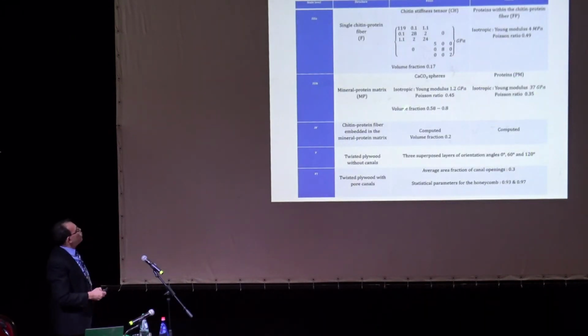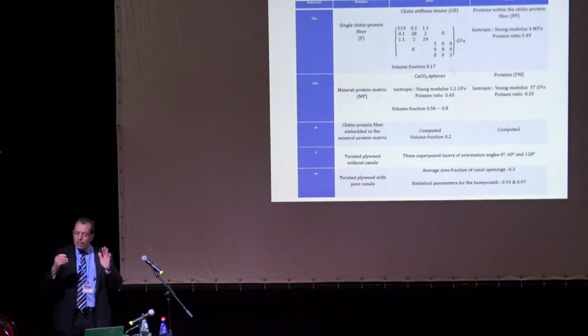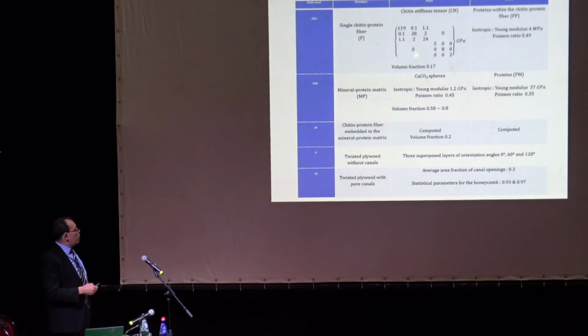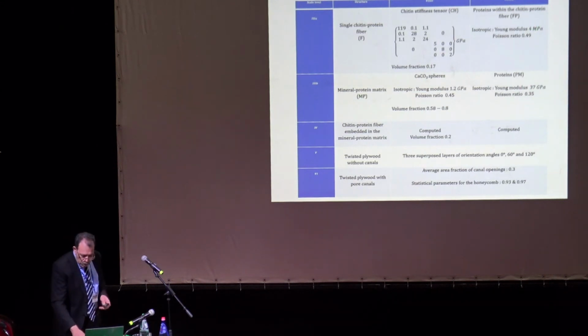Now, just to give you an idea of the properties, you have again a huge contrast here in the properties at different levels, okay? This is the elastic stiffness that they obtained from molecular dynamics, okay? And these are the properties of the matrix to get the fibers. Now at level 3, we have a matrix that has these properties filled by calcium carbonates with these properties, and so on. So we have all the properties here, but the most important thing to retain is we have a local anisotropy at the chitin level, okay, and also we have different matrices at different levels that have completely different properties, from 4 megapascals, for example, to 37 gigapascals. So these are huge contrasts, okay?